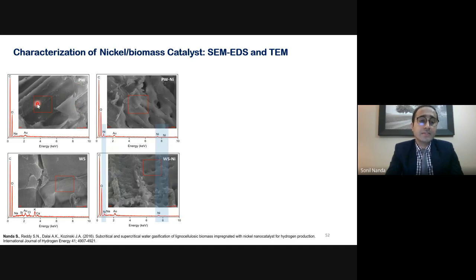You can see here that there is no nickel present here, but in the pine wood impregnated nickel feedstock, you can see the presence of some of the nickel peaks. So as with the wheat straw, there was no presence of nickel, and the nickel appeared in the case of wheat straw when it was impregnated and mixed with the solution.